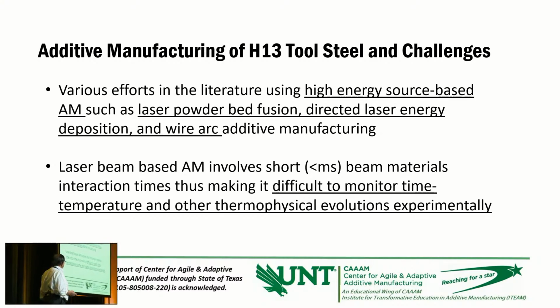So you cannot use the typical infrared cameras to measure the temperature because it's very intense at the laser material interaction zone. Oftentimes, it produces laser metal plasma, and it obstructs the view of your infrared camera, and whatever you measure gives you erroneous results in terms of temperature. If you use any acoustic techniques, the time is so short that sensors often have a slow response compared to the process time. So you cannot use the acoustic sensor, you cannot use the optical sensors, and so on. So it's very difficult to monitor the AM processes. So the only way you can do process predictions or understanding of this process is computational modeling.